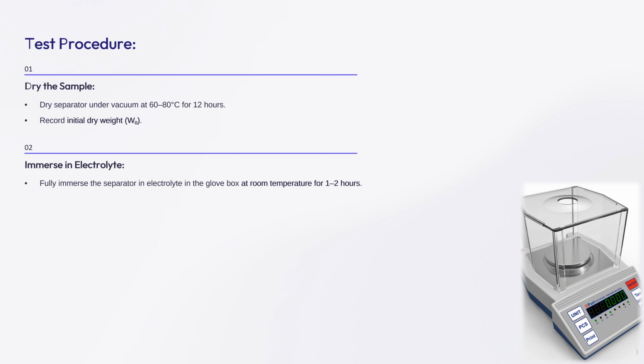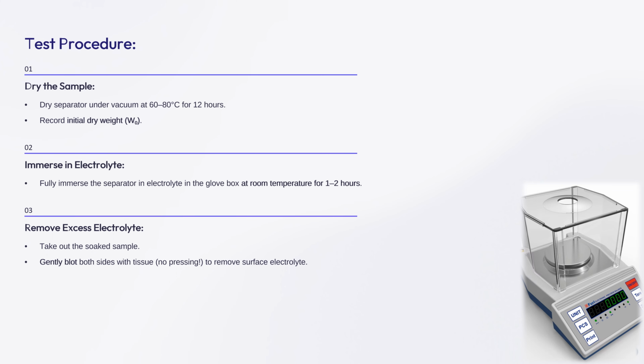Then you can take the separators into the electrolyte, and you can do this inside the glove box or in a dry room, and then soak the separator in the electrolyte for at least 1 hour or 2 hours. After 1 or 2 hours, you can remove the separator from the electrolyte, and then you can gently blot both sides with tissue. But remember, don't press, because when you press, the tissue will absorb a lot of electrolyte even from inside the separator, because it's pretty thin, like 10 to 20 micron. So you should be careful, and only remove the electrolyte from the surface of the separator. So once you remove the surface electrolyte, you can weigh the separator, and you can note this as wet weight or final weight.